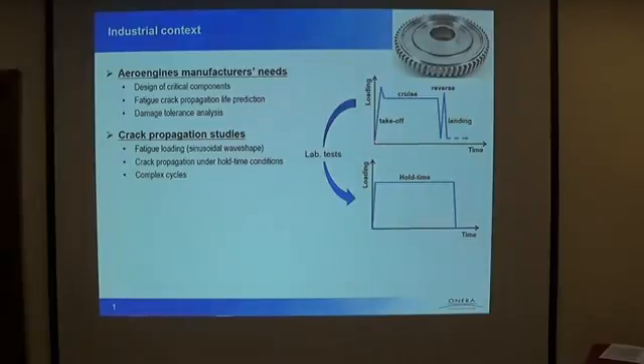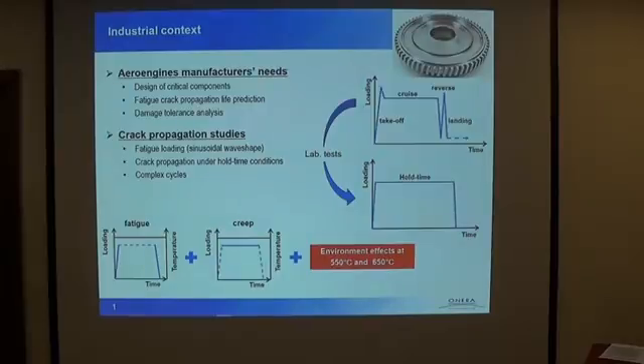However, as you can see illustrated here, the real in-service loading condition is quite more complex, and therefore we decided to investigate the effect of hold-time cycles, like this one, which are, I would say, more representative of the real in-service loading conditions. Assuming such loading cycles, we have to take into account different contributions to the crack growth, which are the fatigue contribution due to the loading and unloading part of the cycle, the creep contribution due to the hold time at maximum load, and finally the effect of environment, since all our tests have been performed at high temperature, and ultimately all the interaction between those contributions.